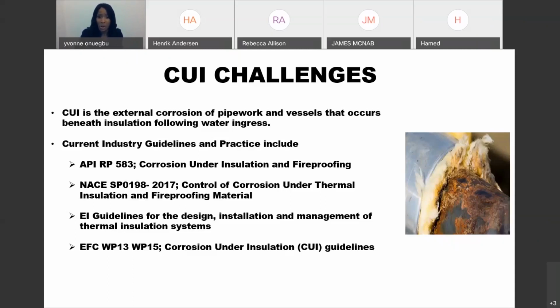And then when we look at maintenance requirements, we're looking at maintenance of the external coating, and at the repairs that need to be carried out on the cladding system. So all these things impact on CUI, but for the purpose of this webinar, I will just pick up on a few of them. If we're talking about costs, CUI presents a high expense in terms of failures, remedial work, deferment, and inspection activities. According to the Oil and Gas Technology Center, about 20% of major incidents in the oil and gas industry in the European Union region since 1984 have been attributed to CUI. And even in the North Sea, more than 60% of pipework failure is due to CUI.